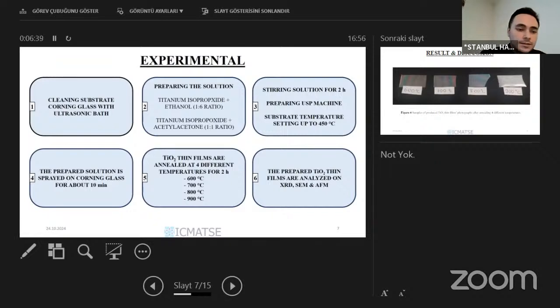After that, everything is ready, and our prepared solution is sprayed onto the Corning glass for about 10 minutes. Because of the heat, we should wait inside the machine — we shouldn't take out the glass, because of possible cracking. It can be cooled down inside the machine.